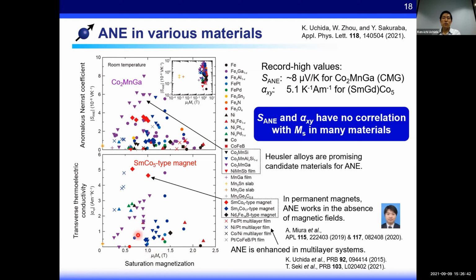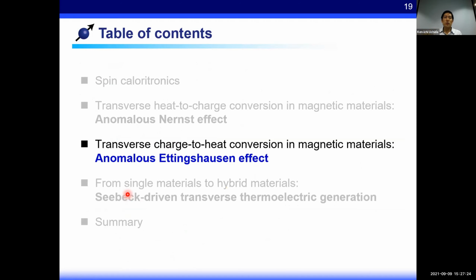As shown here, the large anomalous Nernst coefficient was obtained in Heusler compounds, such as Co2MnGa, CMG. As far as I know, the record high alpha xy was obtained for SmCo5 type magnets at room temperature. Importantly, these parameters have no correlation with saturation magnetization in many materials. This is partially due to the fact that the intrinsic mechanism plays an important role in the anomalous Nernst effect. Through these activities, the thermoelectric performance of the anomalous Nernst effect has been improved dramatically in the past few years. Okay, next I will show our recent progress on the reciprocal process of the anomalous Nernst effect.